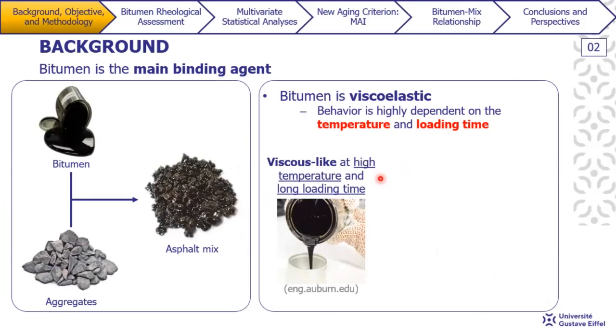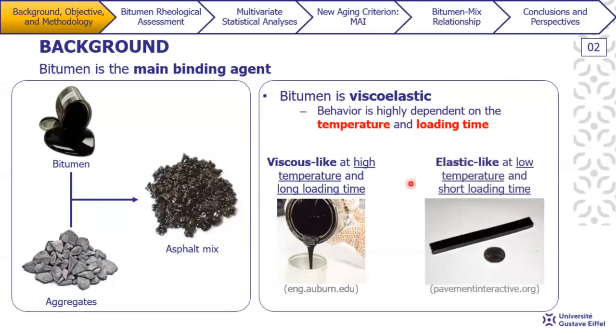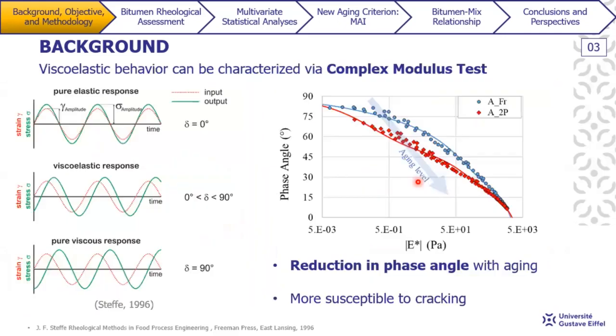At high temperature and long loading time, bitumen behaves like a viscous liquid, whereas at low temperature and short loading time, bitumen will be behaving more like a solid or elastic-like material. So due to the wide range of bitumen's behavior, complex modulus tests have proven to be very effective in characterizing asphalt mix, as they encompass a wide range of temperatures and frequencies, and they are closer to the conditions our asphalt materials will be subjected to in the field under different climatic and traffic conditions.